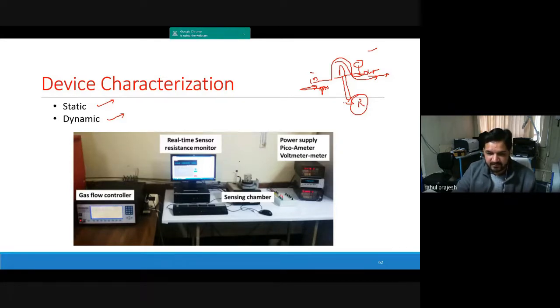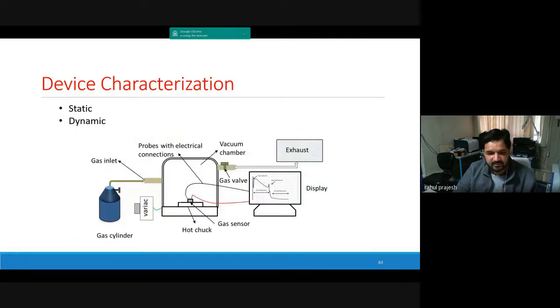So this is a complete setup where you see this is the chamber where you put the sensor. This sensor is driven by one supply for the micro heater and the measurement of sensing film resistance. This is the computerized system where you have different MFCs. At times we can use 4 MFCs in this system. So 2 MFCs, one is for the target gas, one is for oxygen, air. You mix different proportions of the gas to make different ppm concentrations, and you push that into the chamber, and the chamber is connected with the supplies and meters. This is the schematic of the same setup where you have this chamber. This device is connected to the monitor as well as the supplies. You have a cylinder which goes inside the chamber.